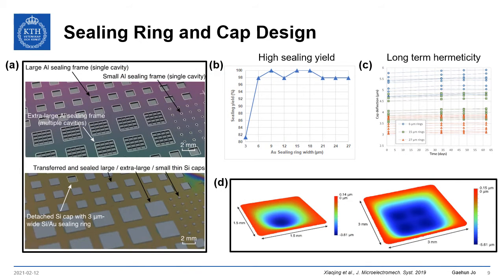For evaluating the wafer scale sealing yield, which is shown in figures A and B, a total of 432 silicon sealing caps were fabricated on a 4-inch wafer. As shown in figure B, after transfer bonding, the thin silicon sealing caps with different sealing ring widths had an excellent yield of above 98%, except for the 3 micrometer ring width. It is because these thin sealing rings do not provide sufficient bond strength as a result of the small bonding area.